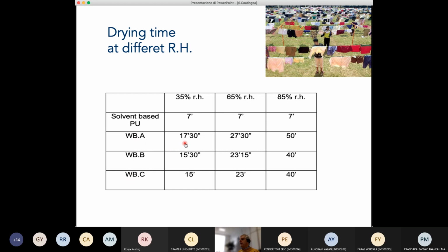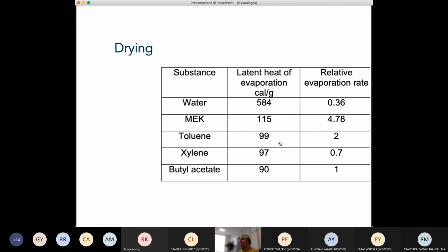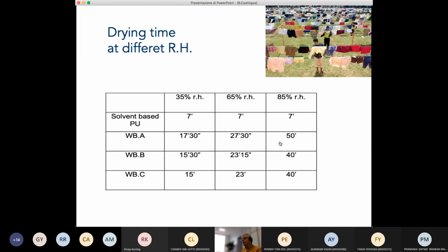You can see that at a very low relative humidity, the drying time is relatively fast, around 15 minutes. If we improve the relative humidity to 65%, the drying time increases, and when we reach 85% relative humidity of the air, the drying time of water-based coating is very, very slow, taking from 40 to 50 minutes. So again, in the case of water-based coating, you must use an oven, and maybe it's better to control not only the temperature but also the relative humidity.